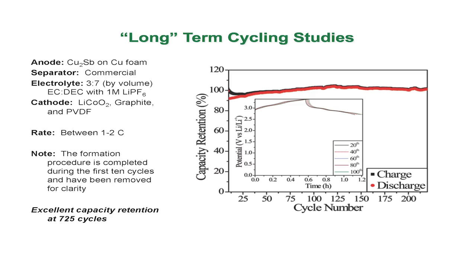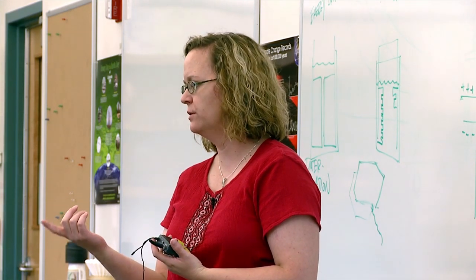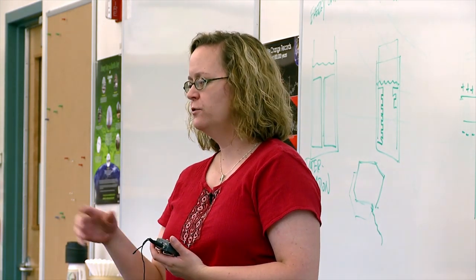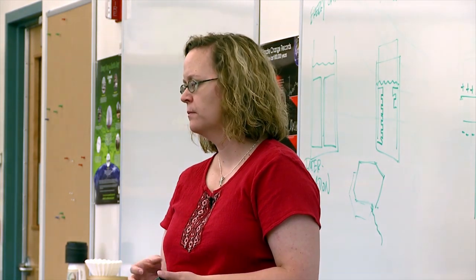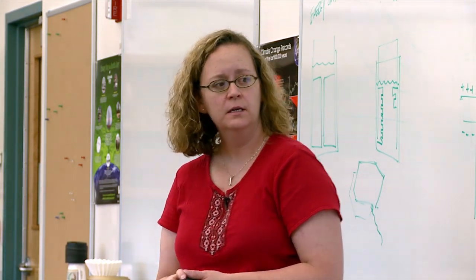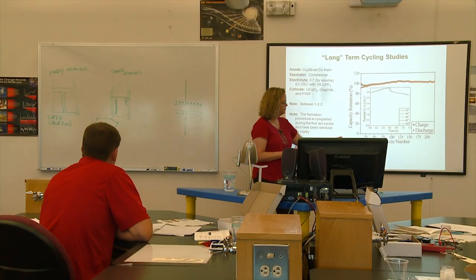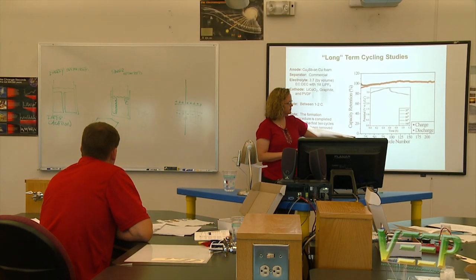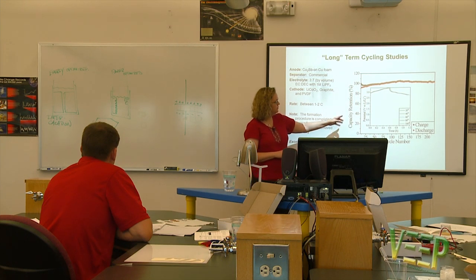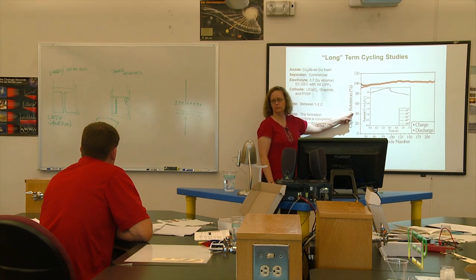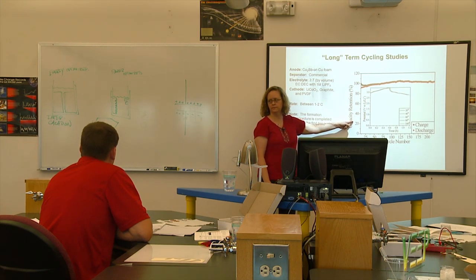Now, the key is that we cycled at a rate of 2C. So a C is fully charging and discharging your battery in 1 hour. Your cell phone's rated to work at about C divided by 3 or C divided by 5. And so we were going pretty fast. What's important here is that if we go out to, in this plot I'm showing you, about 220 cycles, this is the percentage of capacity retained from where we started.